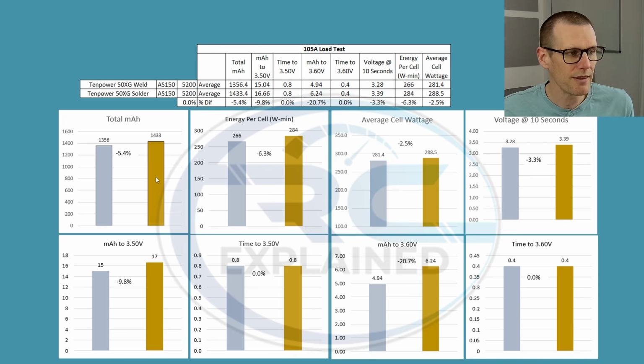When we're taking a look at these graphs, the blue bars represent our welded pack configuration, and the gold bars represent our soldered pack configuration. When we look at our total milliamp hour for the pack, we deliver 1433 on our soldered pack versus 1356 on the welded. Energy per cell at 284 versus 266. Average cell wattage was about 288.5 versus 281.4 for our welded pack.